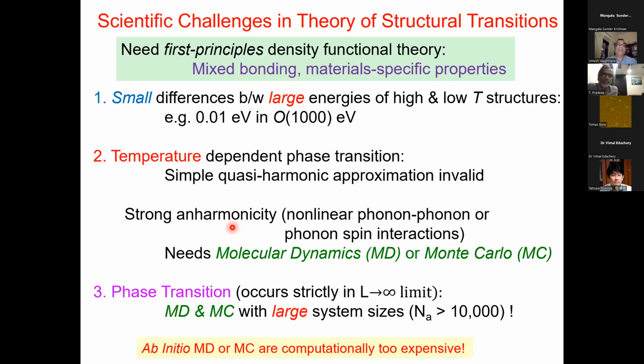So let me summarize what the scientific challenges are in the theory of structural transitions in crystals. First of all, you do need first principles density functional theory, because, for example, barium titanate has a very mixed type of bonding, which involves covalency, ionicity, and also pd interactions between d and p orbitals of titanium and oxygen. And the material-specific properties are to be predicted. You don't have any other option but to use first principles density functional theory at present. And this is the only theory which can capture the small energy differences between very large energies of high and low temperature structures.